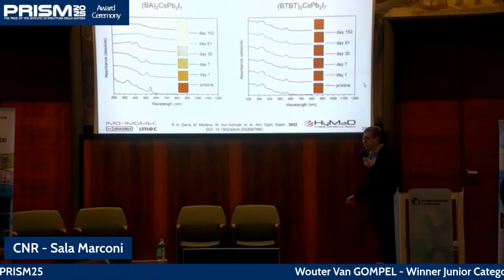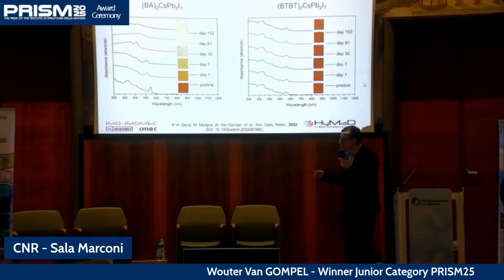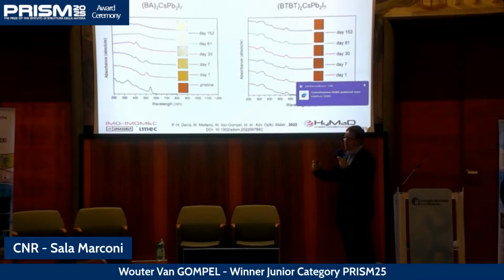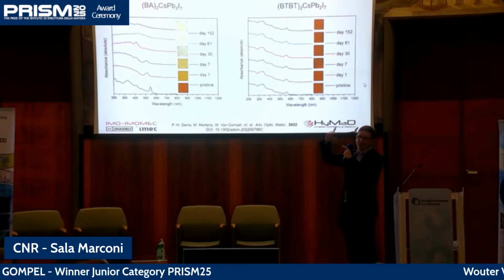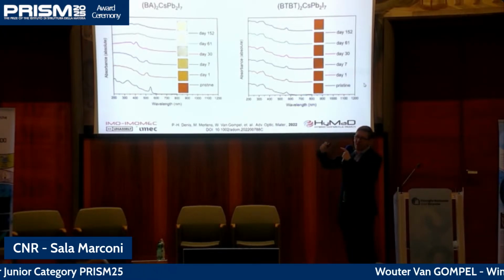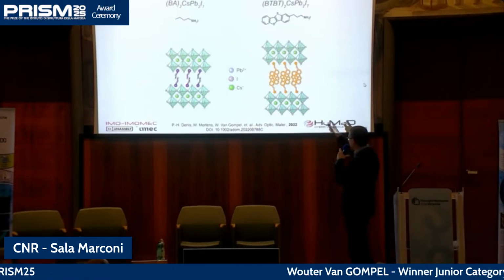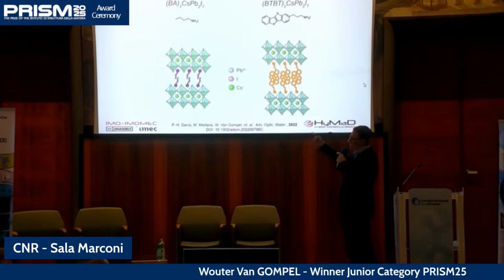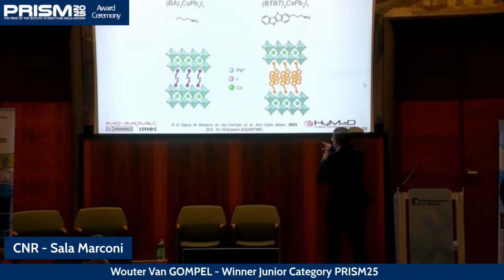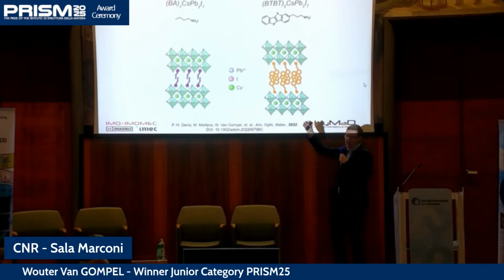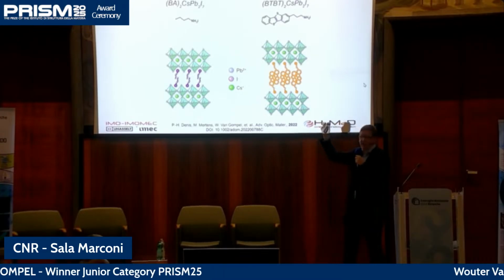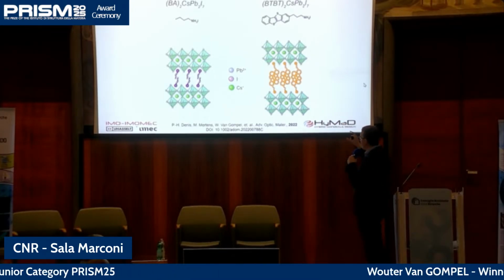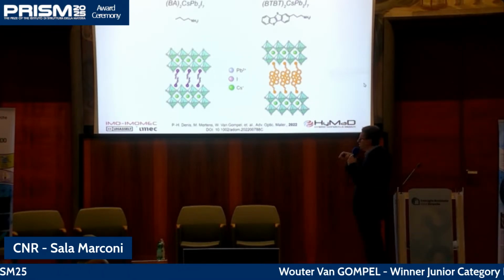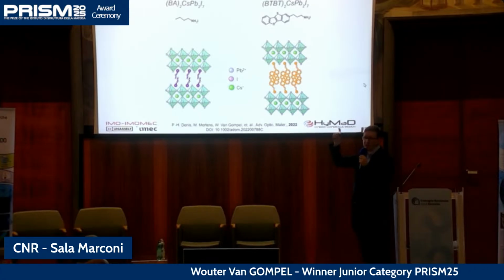No, but the d-spacing is almost exactly the same as you would have if two of these molecules were really stacked on top of each other, forming a bilayer. Of course, like for example in this one, just the length of this molecule, if you make a bilayer, you will separate the inorganic to a much higher extent, and if you count twice the length, you come almost to this d-spacing that we have here.